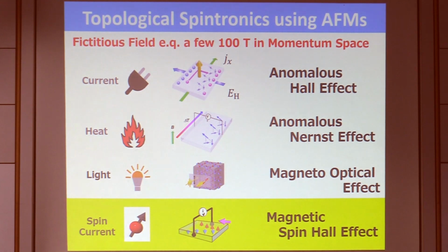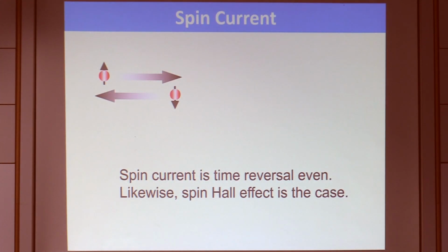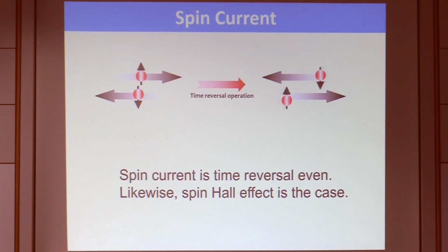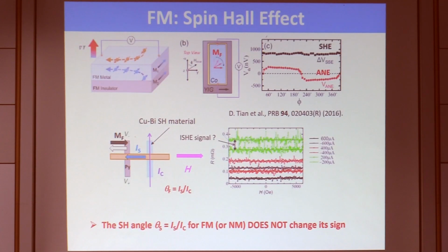Okay, I would also like to touch on the spin Hall effect, which is obviously a time reversal even quantity, as spin current is time reversal even. The angular momentum is flowing from left to right, and under the time reversal operation it's actually the same. So it's a time reversal even quantity, and this has already been tested in ferromagnets, where time reversal symmetry is obviously broken macroscopically. The spin Hall effect sign doesn't change, although the anomalous Nernst effect does change with magnetization reversal. This is for cobalt, but for permalloy it has also been seen by using non-local measurement in another laboratory.